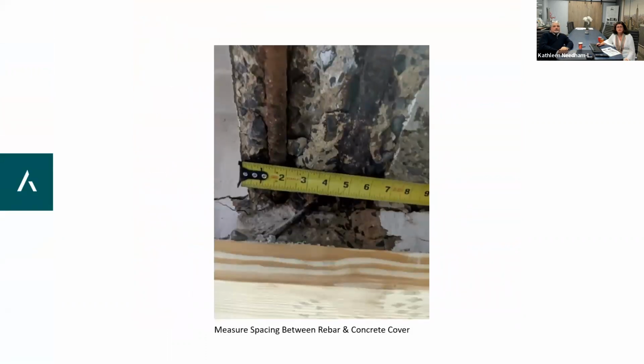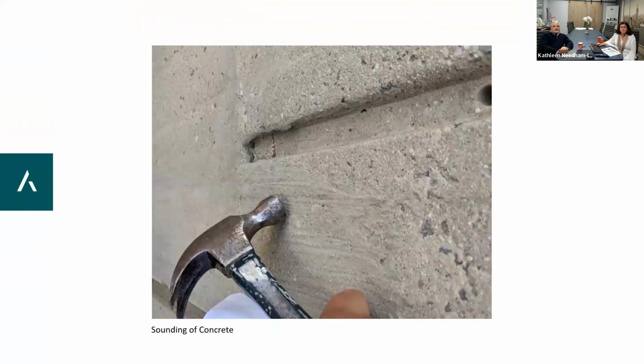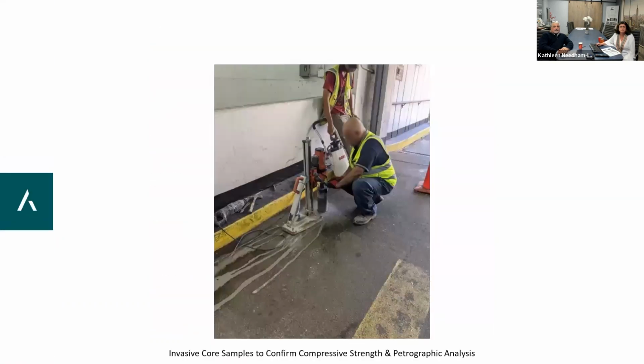And here, measuring spacing between rebar, we're measuring the spacing of the concrete cover, which protects the steel rebar from oxidation. We'll take a simple hammer, it might be a rubber mallet, and every engineer has their own technique and own instruments they like to use. We want to sound out, and as I said, the building department requires 10% of the structure be sounded out by the engineer. You're listening for hollow sounds or things that may be indicative of a problem where the cracking hasn't come through the concrete yet.